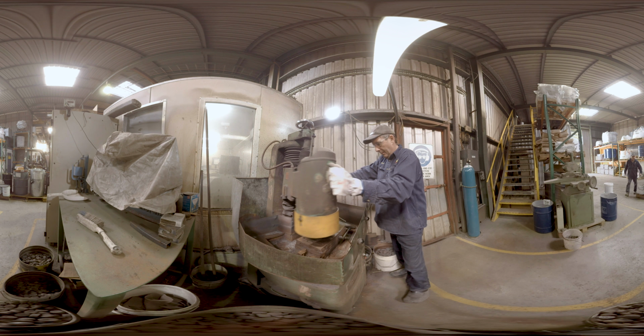To maximise the reuse of low alloy steel runners and risers, a carbon boil is used to remove impurities such as sulphur and phosphorus. Oxygen is blown through a lance to create a reaction between the metal and the fluxing agents, which moves the impurities from the metal to the slag, creating a clean steel.